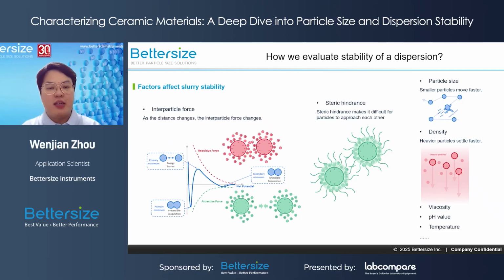Another important factor is the particle density. If the suspended particles are much heavier or lighter than the liquid around them, they tend to settle or float more easily, which lowers stability. And finally, we shouldn't forget about other conditions like viscosity, temperature, and the pH. All of these can influence how stable the dispersion is.